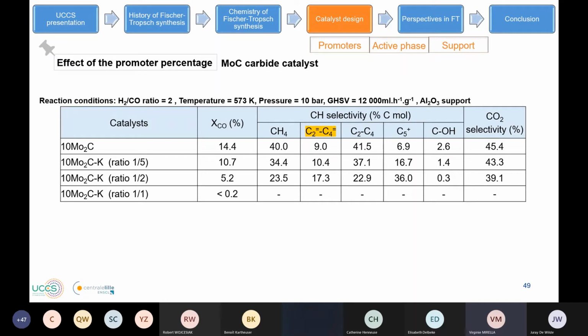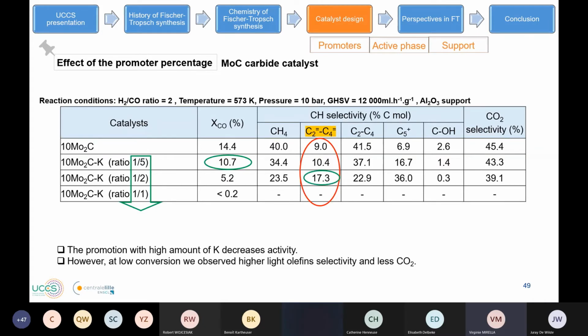So here also we varied the ratio of molybdenum to potassium, and we observed that when we increase this ratio, so when we had more potassium, we have a decrease in the conversion. So we have higher conversion when we had not too much promoter. Then when we have a look at the selectivity into olefin, we observe that the selectivity of olefin increases with the reduction of the conversion. So at low conversion, it seems that we have higher olefin selectivity.